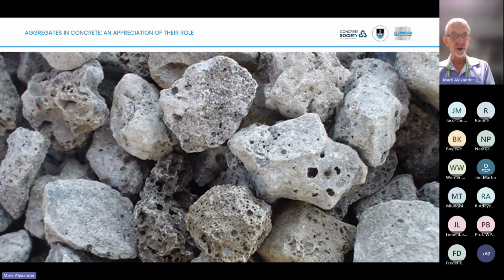Now, over that whole range of aggregates, the difference in water requirement, if those were used in concrete, would probably be about 50 liters per cubic meter. Now, you take a water cement ratio of 0.5, that would translate into about 100 kilograms of cement. If you use the most, let's say that was the lowest water demand.